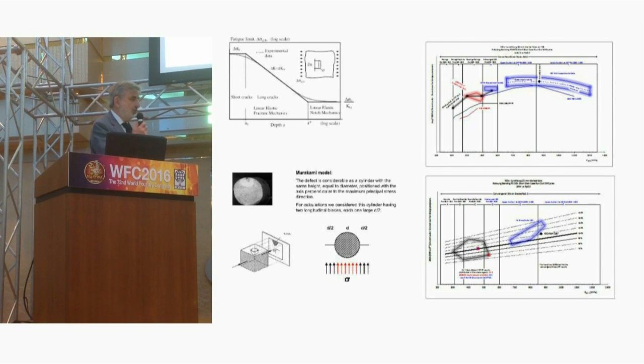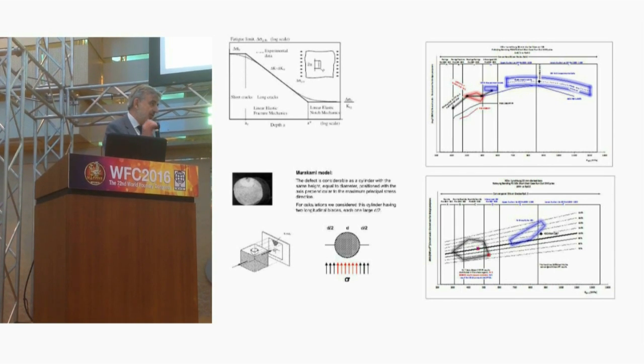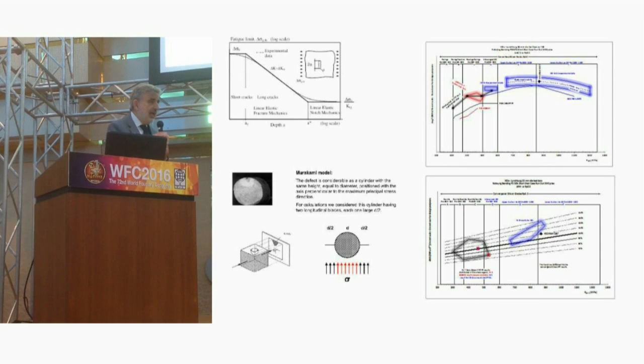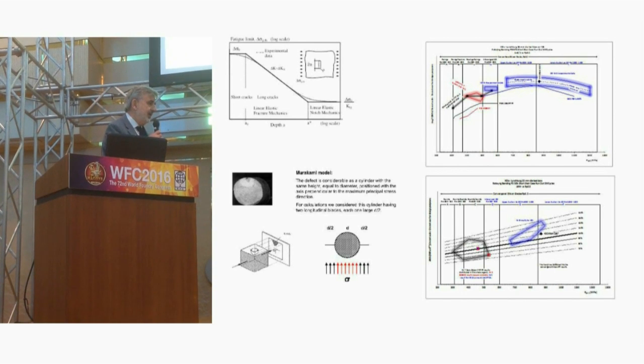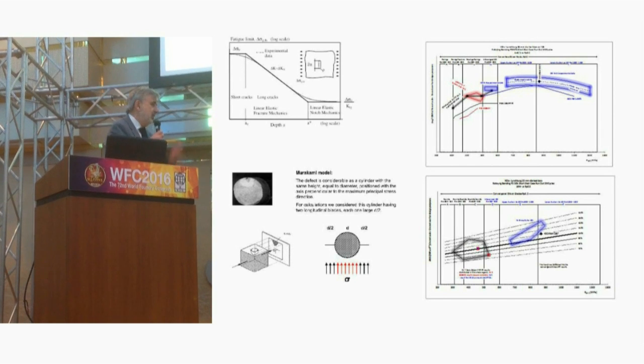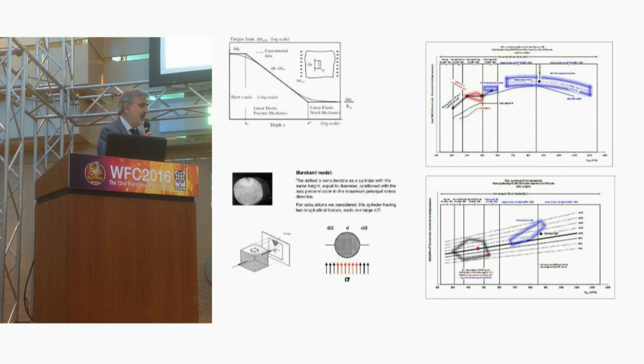Yeah, we normally cooperate with our customers in co-design using the Murakami approach. So we define the defects that are allowed in the given section, and with these defects, their shape, we define the square root of area perpendicular to the principal maximum stress. And with this, we transform this defect into an equivalent crack, and we go on our Kitagawa diagrams modified by the KT to make the evaluation of the expected fatigue strength in presence of defect, probability of survival of 50%. Then we have our sigma for the dispersion, and so we calculate with the usual diagram with our customers.